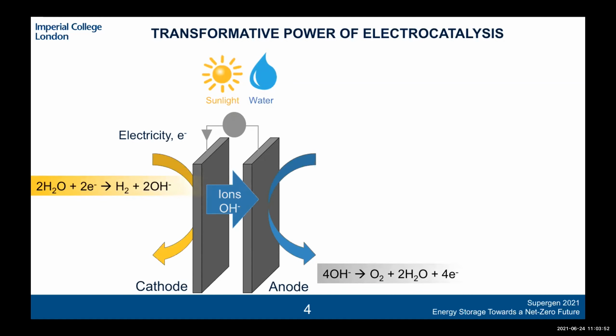So while hydrogen is the gas that we're really interested in, if we look at the energetics of the overall reaction, we see here that the oxygen evolution reaction has a significant amount of energy loss during this reaction. So the materials-based challenge remains to figure out materials that can catalyze this oxygen evolution reaction at a faster rate and reduce this overpotential that's required, especially at high current densities for overall water splitting.